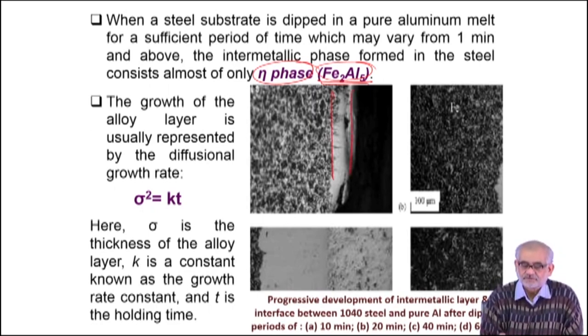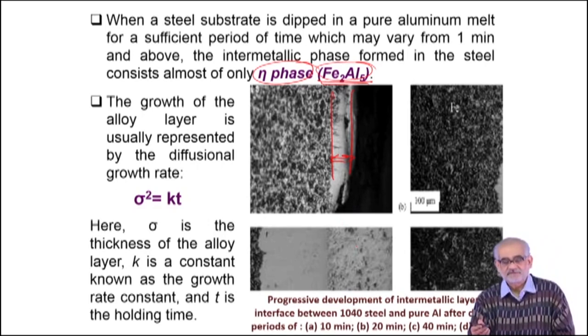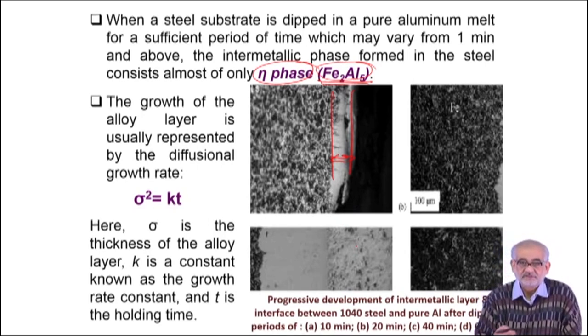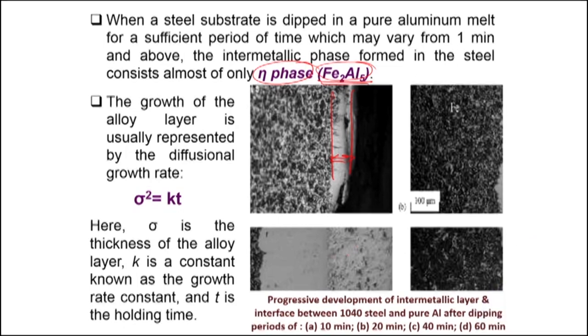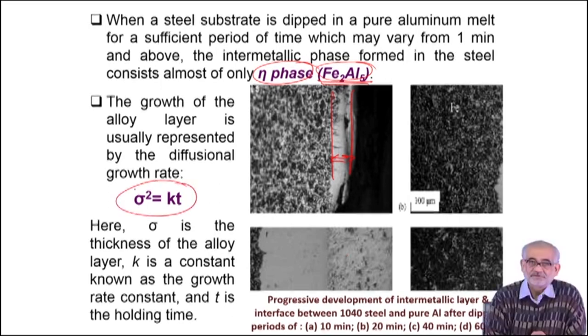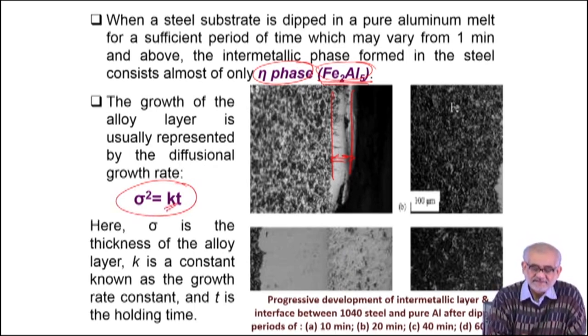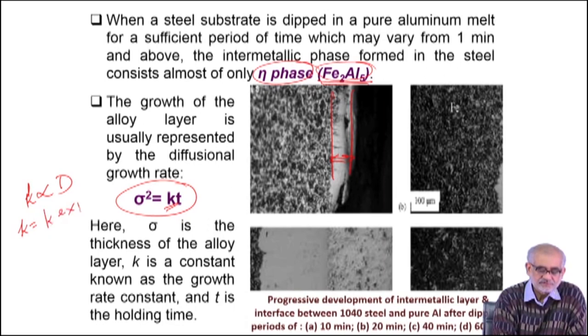This aluminium-rich barrier layer will grow with time if we increase the residence time in the diffusion coating chamber. The cross section shows it is not pure aluminium — it is actually an aluminium-rich matrix phase with many intermetallics. The thickness of that layer essentially depends upon time at a given isothermal condition, and the constant k here is proportional to the diffusion coefficient. One can write k very similarly to a diffusion coefficient equation and determine its value at a given temperature.